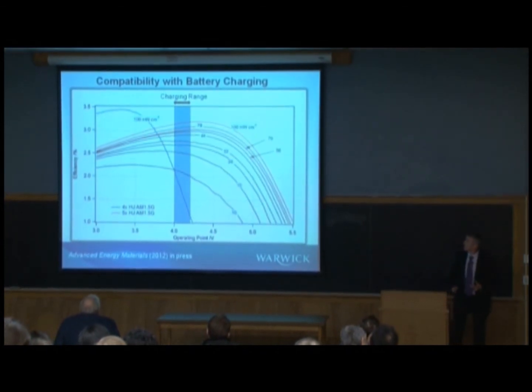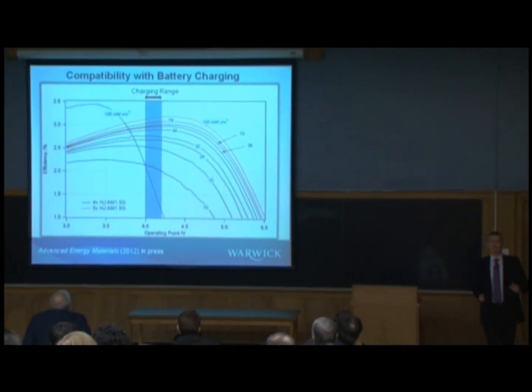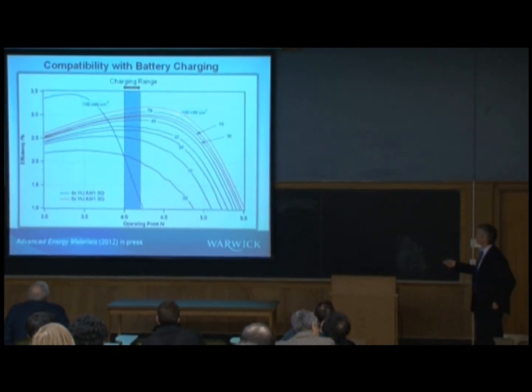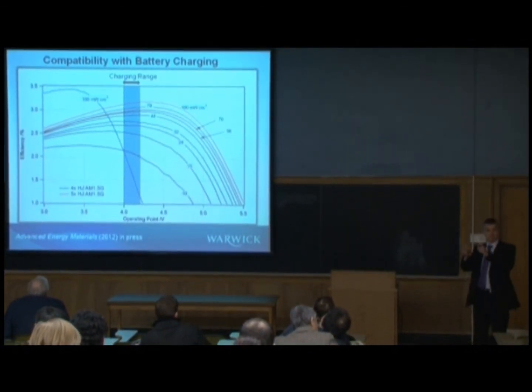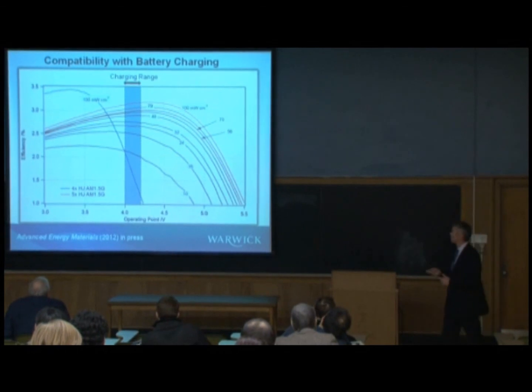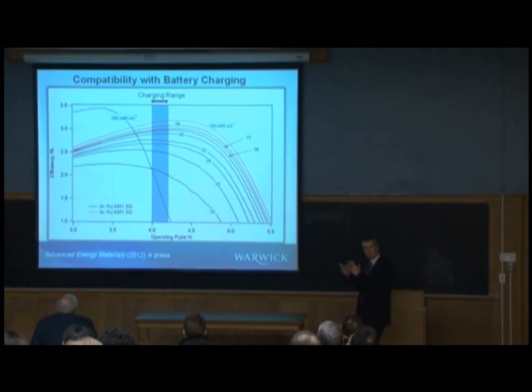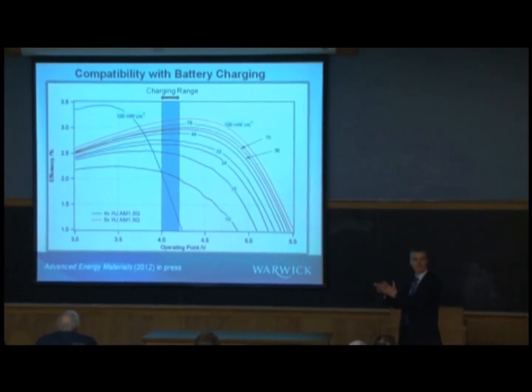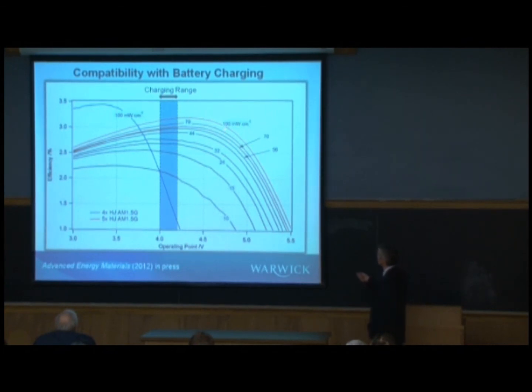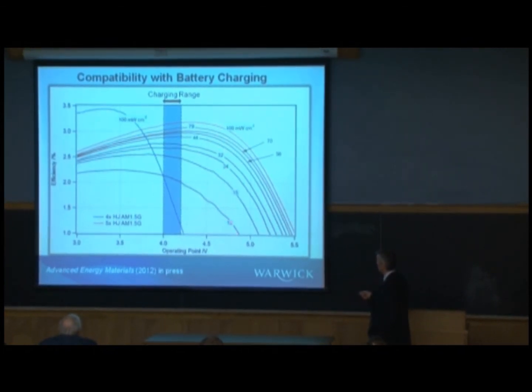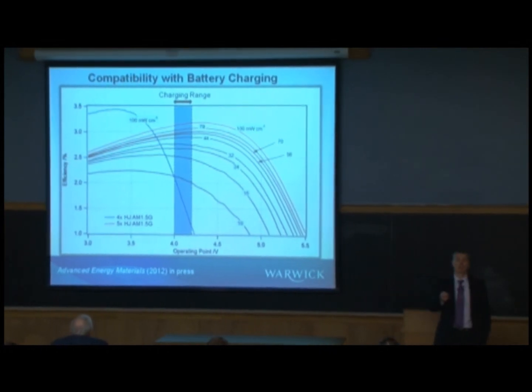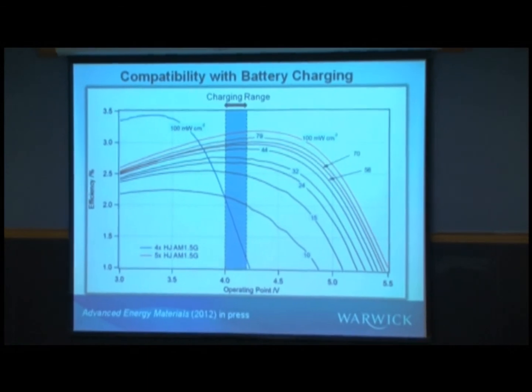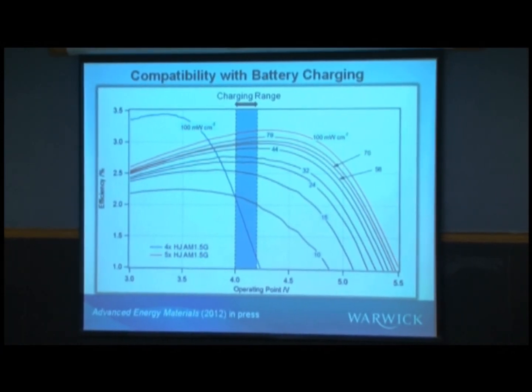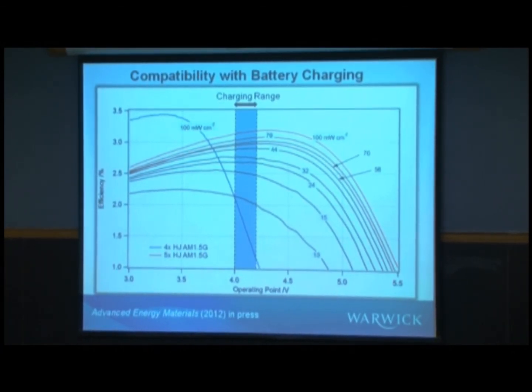So if you go down in power, the calibrated standard is 100 milliwatts per square centimeter. All the current voltage curves I've shown you use that standard. That's really compatible with putting your cell outside in sunny conditions. But as you reduce the power, even at 10 milliwatts per square centimeter, you've still got a voltage that is sufficiently high to power your device. So the voltage doesn't decay very significantly. So that's very important.